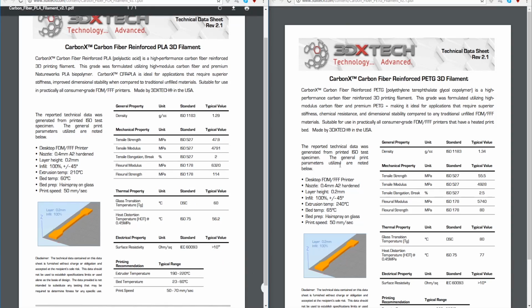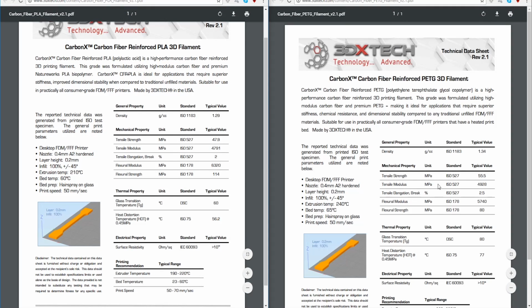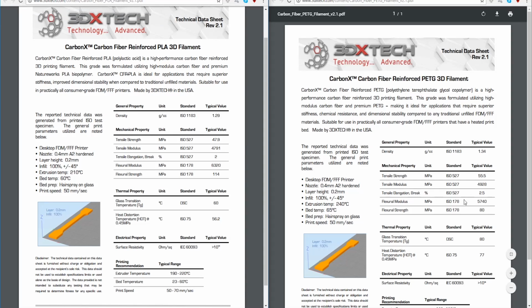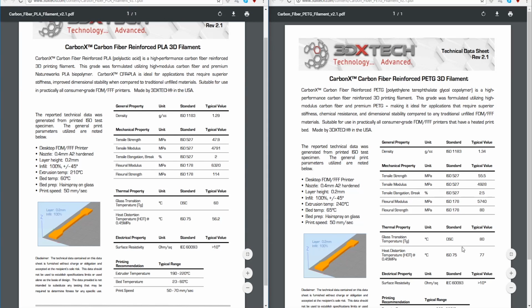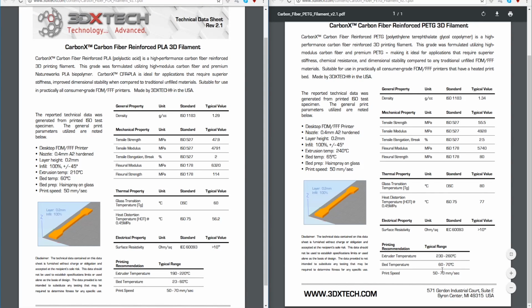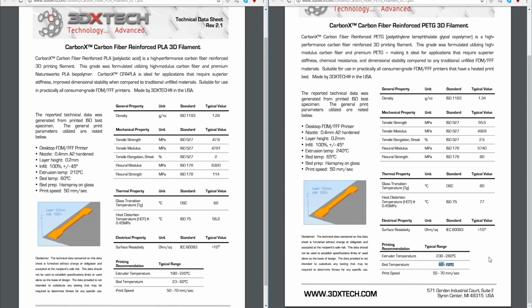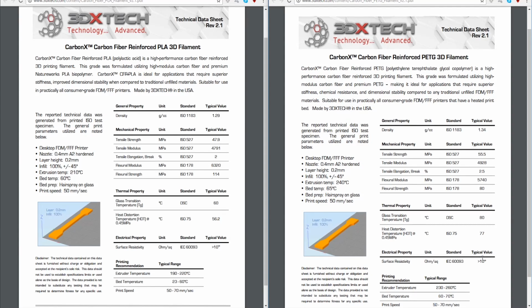Alright, carbon fiber PLA. Let's take a look. Whoa, stronger, bigger modulus, more flex, but not as good in a flexural state, so not as good in bending. A little bit better stability, but you need a heated bed. Not nearly as hot, so maybe you could get a Printrbot Simple to hit that temperature, possibly. Okay, so carbon fiber PLA versus the carbon fiber PETG.